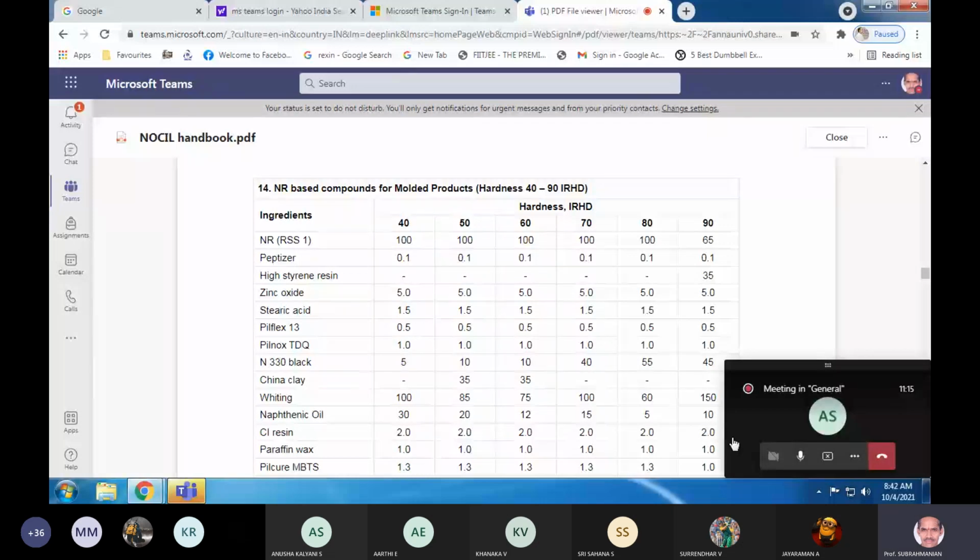What stays longer in the rubber need not give effective protection, because effective protection means it has to be chemically active. Anti-ozonants are for dynamic cases. Dynamic meaning cyclic loading is involved, like tire sidewall, tire tread.